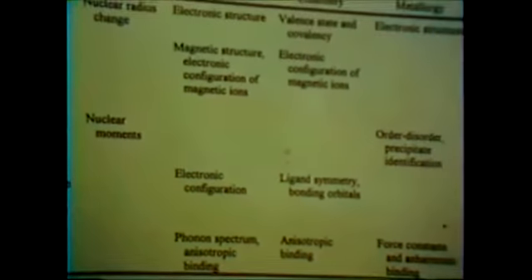But in solid state physics, you learn about the electronic structure from the isomer shift, like I mentioned. From the magnetic hyperfine field, you learn about the magnetic structure, the electronic configuration of magnetic ions. You learn from the electric quadrupole the electronic configuration and the symmetry, if it's cubic or less than cubic. And from the recoil-free fraction, of course, you learn about the vibration of the atoms suspended on the lattice, so you learn about the phonon spectrum. Same thing with chemistry, you learn about the valence, electrons, covalency, electron configuration, ligand symmetry, and anisotropic binding. Metallurgy also uses it, biology uses it, analytical chemistry also uses it.